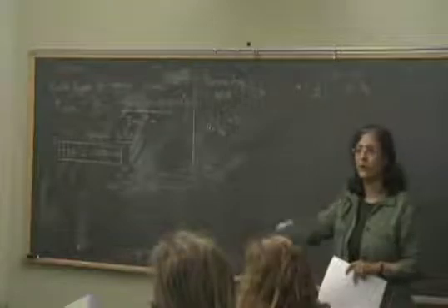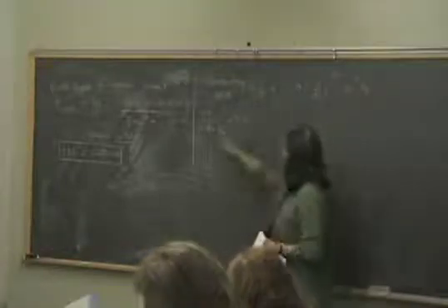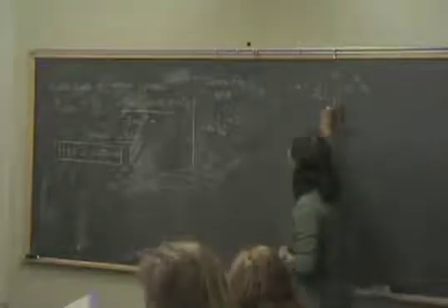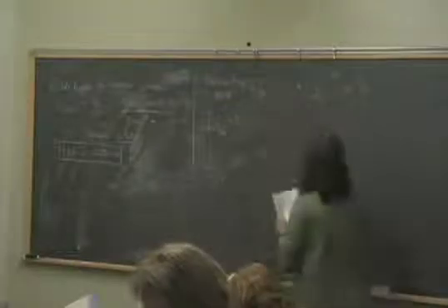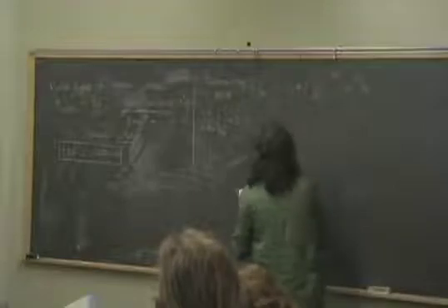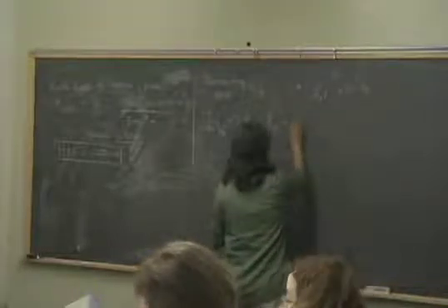So now you can see, for once, I can't just do my order one all the time, because these numbers become a little important. So for the first time I had to go back and really put the numbers in. But otherwise this is a number of order 1, but that 3 will become important. Because as you saw, all these big powers cancelled, and it was finally the little 3s and 5s which gave us the 2.5. Okay, so if I take this, put it all in, and I won't waste your time with that, then E plasma turns out to be 9.1 eV.